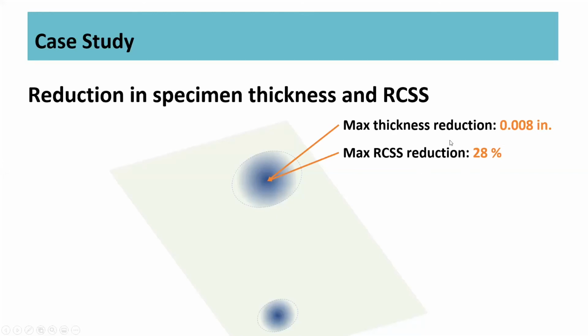So certainly if we were at the minimum of 10,000 and we reduced it 28%, we're clearly not in our minimum 10,000 range. Now, it's also worth noting that when we polish glass, as I mentioned, we're typically not doing the entire unit. We're using some localized area that we're trying to get rid of these blemishes. So it depends, again, going back to that case-by-case basis, on what's going to be reasonable or not reasonable as far as this goes.